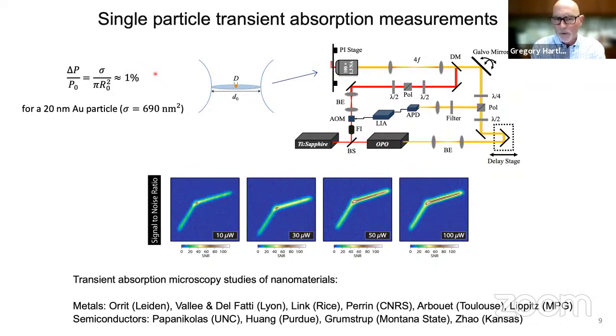We're doing transient absorption experiments. In transient absorption experiments, the signal levels are typically about 1,000 times smaller than the linear absorption measurements. So you'd expect a single metal particle to give you a transient absorption signal of about 10 to the minus 4, 10 to the minus 5, right? That would be the change in the transmission. Okay, so that's very small. But if you have a very stable high frequency laser system and you do tricks like high frequency modulation, you can measure signals as small as 10 to the minus 7 or so in differential transmission.